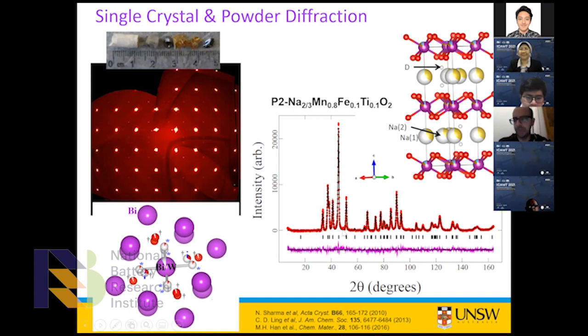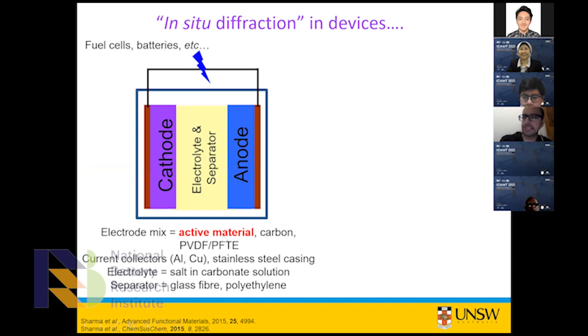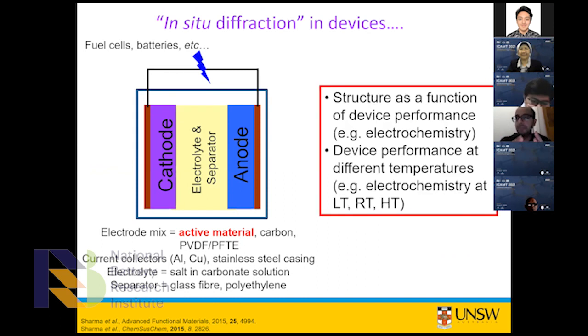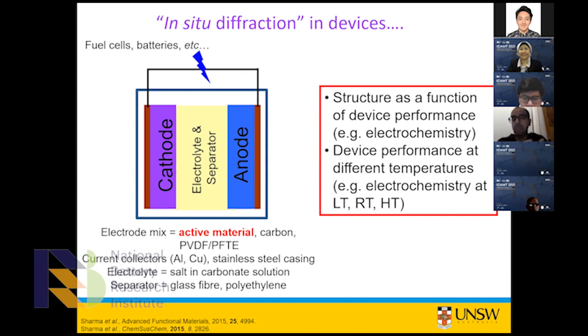When you start thinking about in-situ work, you have a very complex system — multiple components including cathode, anode, crystalline and amorphous components. You're fitting multiple models to one evolving dataset as you charge and discharge. But if you can see what's happening, you can find out not just across one charge-discharge cycle but across different current rates and temperatures. You can work in a large parameter space as long as you get the models right. Diffraction is quite good because batteries only have a few crystalline things it's sensitive to.